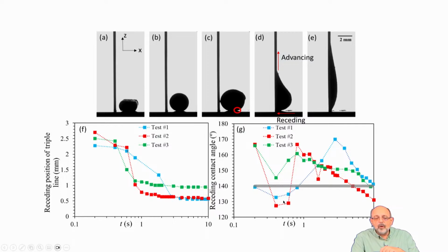But what we see here, the contact angle goes up, although it is a receding contact line. Most experiments with the receding contact line give us that the contact line approaches the equilibrium contact angle from below. When it's an advancing contact line, you are pushing your surface, so you approach from above. But here you have dynamics which forces the contact angle above the equilibrium contact angle.